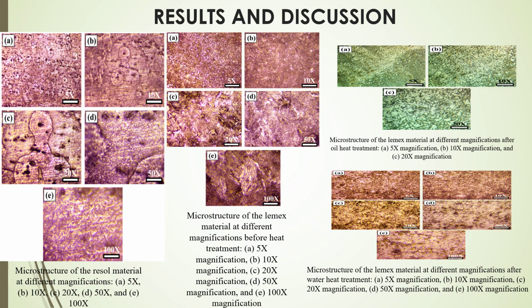First, we examined the resol material at magnification from 5x up to 100x. This structure showed uneven grain distribution and weaker bonding, which explains its lower wear resistance. Next, we analyzed the Lemex material before heat treatment. Although it had a better structure compared to the resol, the grains were still relatively coarse and not fully uniform, which could reduce durability under heavy soil contact.